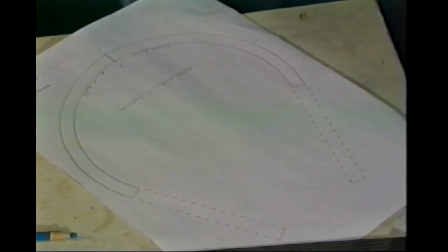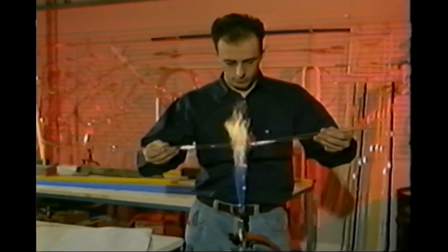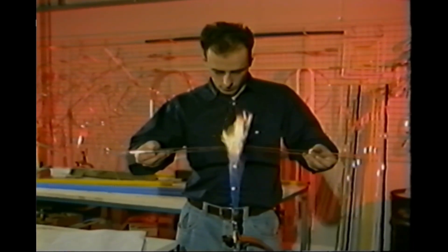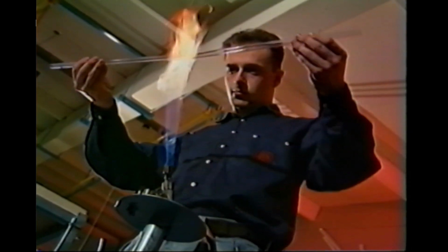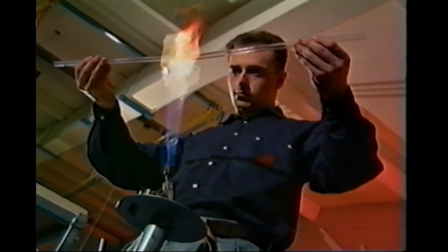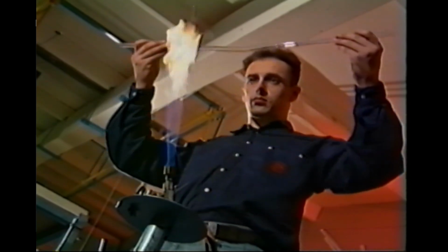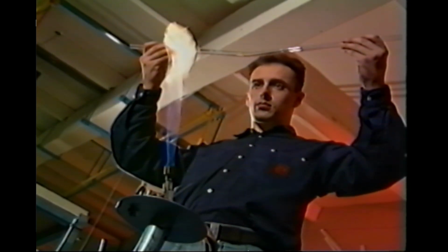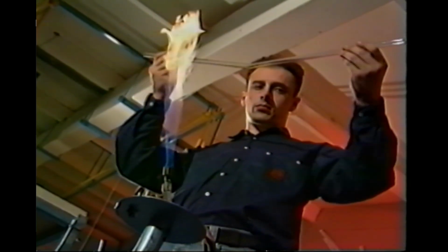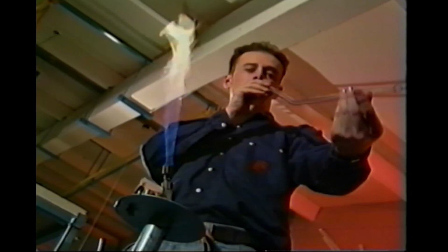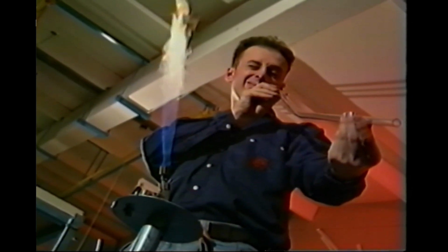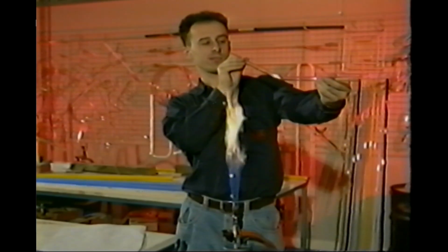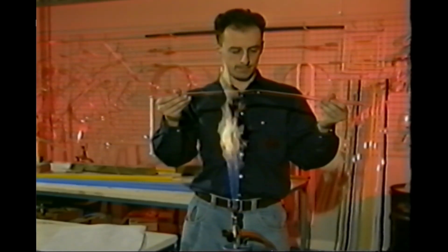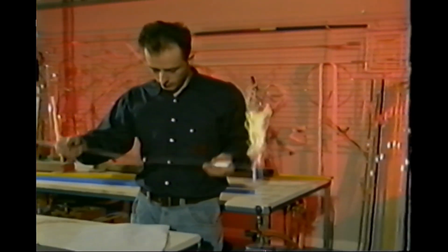Return the glass to the flame, and now with the back and forth rotation, soften the area where the mark has been placed. Again, when the glass softens, remove the tube from the flame and raise the tube to head height. Move the right side arm up to produce a second slight bend at the mark point. Turn the tube at eye height, giving a view down the length of the tube, and check or correct alignment to keep the bend section flat.